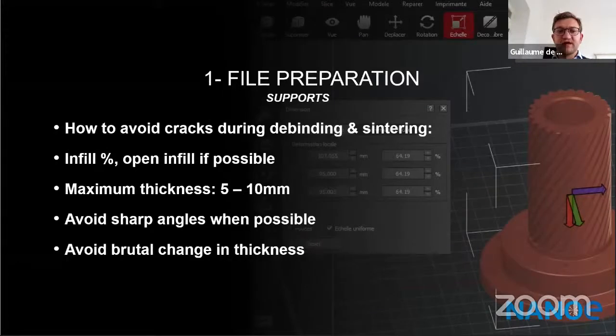The first one is we need to avoid having high thickness. If you have thickness of more than 5 millimeters, you're starting to be in a, let's say, dangerous region, and we know that more than 10 millimeters of really dense material, of fully dense material, is impossible. We can't make it. So how do we go around that problem?